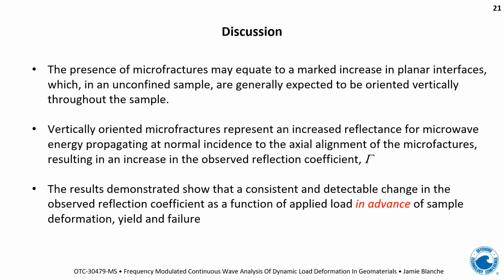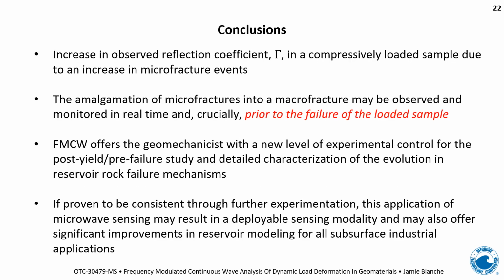These results show that a consistent and detectable change in the reflection coefficient as a function of applied load in advance of sample deformation yield and failure can be observed. So I'll round off with what we've concluded then. An increase in observed reflection coefficient in a loaded sample is due to an increase in microfracture events. We can see that the amalgamation of microfractures into a macrofracture may be observed and monitored in real time, and crucially, prior to the failure of the loaded sample. It now has a predictive capability.